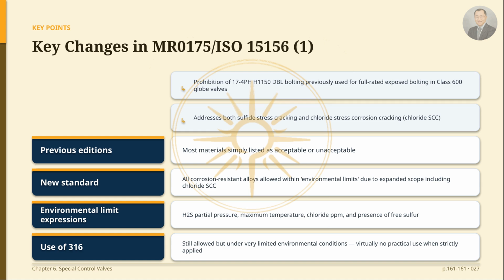These environmental limits are typically expressed in terms of H2S partial pressure, maximum temperature, ppm chlorides, and the presence of free sulfur. Third, the use of 316 material is still allowed, but only under very limited environmental conditions. If strictly followed, this material will find very little use in practice.